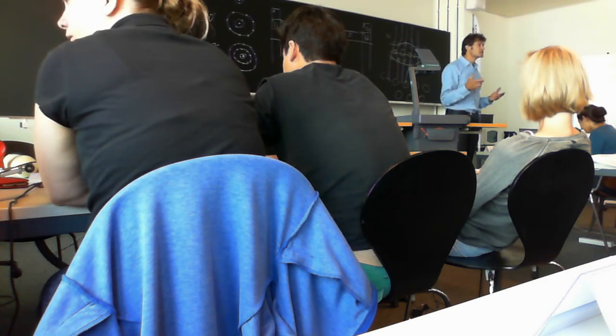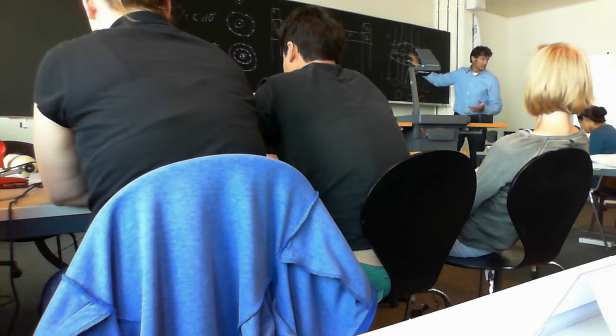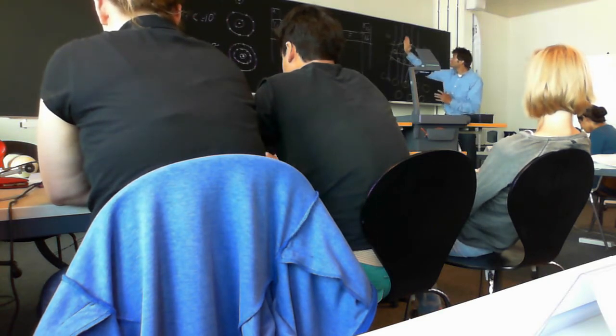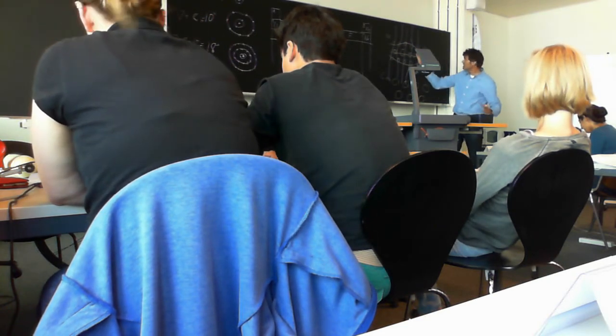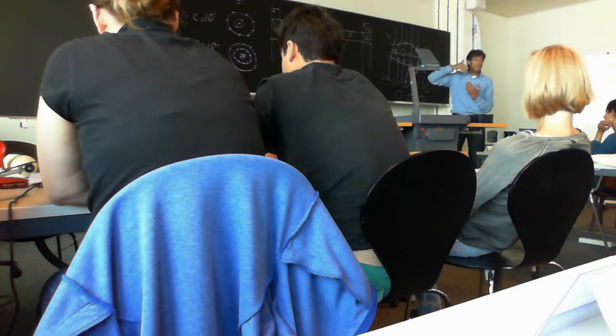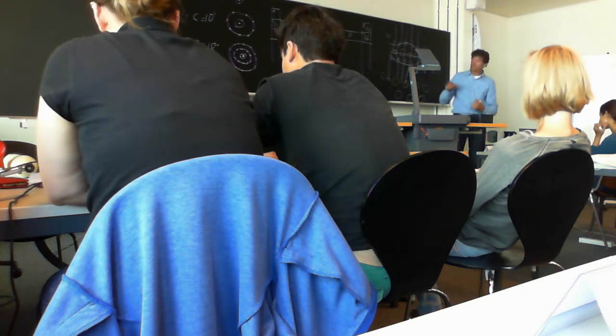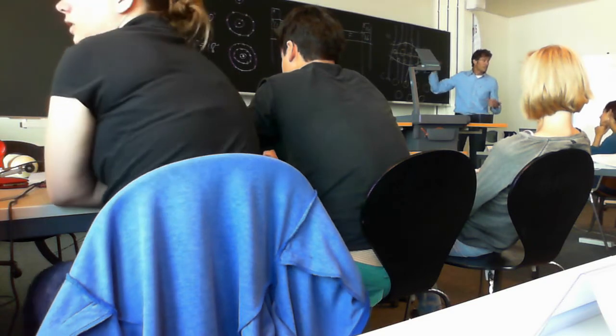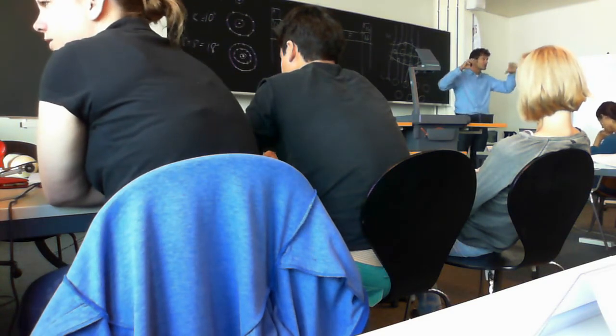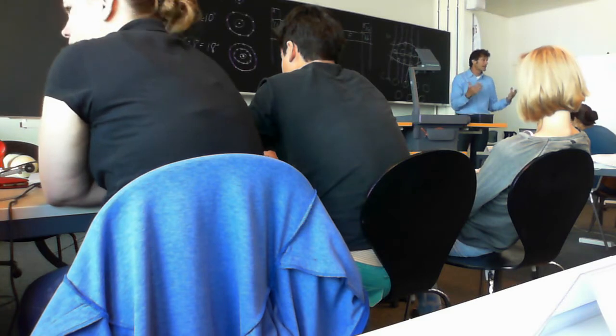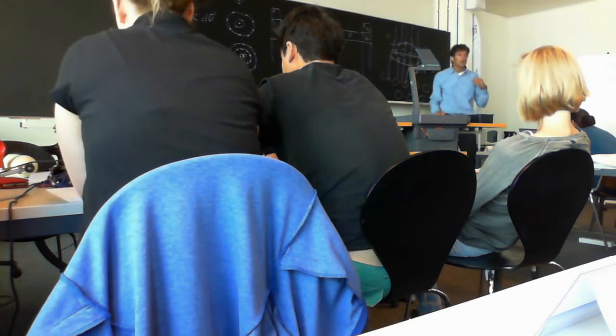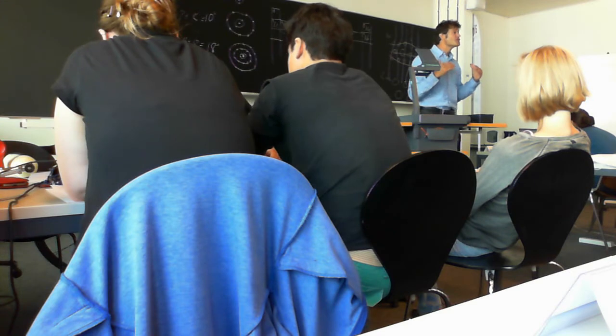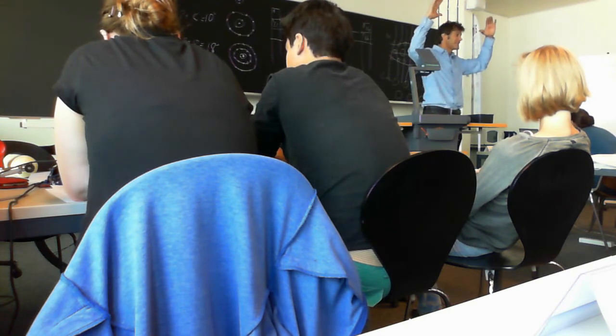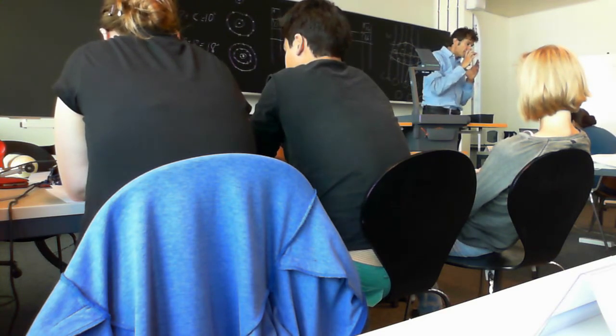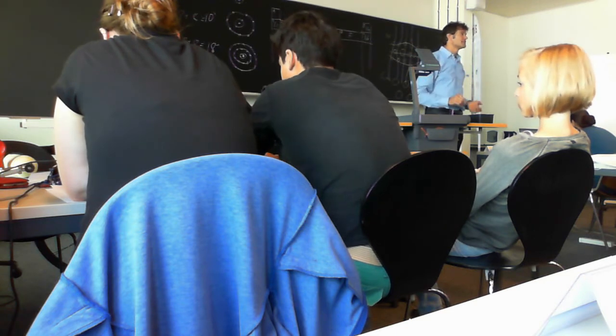Progressively, they made improvements using alloying elements to create distortion, to make it more difficult for the dislocation to go through. The dislocation gets stopped here. In order to get the dislocation moving, you have to bring more force into the system. It means you can go higher and it will still come back. You don't get to move your atoms around, so you still have the same shape. So progressively, they've improved the elastic limit. They brought it higher and higher and higher, and because of that, the carabiner could be made lighter and lighter. Today, the lightest carabiner, I think, is 22.5 grams.